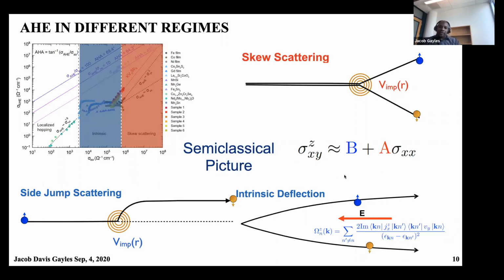You can classify these into two groups. So the conductivity, you can separate into one term called B and one term A. A has some dependence, and the original way was linear. Now people see more, it can actually be a square dependence, which is what we found for the vanadium antimony. And then you have the intrinsic and side jump terms, which are independent of the longitudinal scattering. And this you can see very clearly in the intrinsic regime, where you have this flat plateau of all the materials.